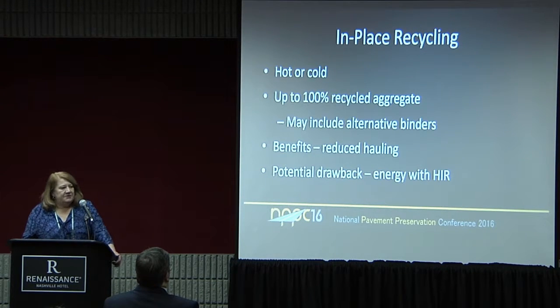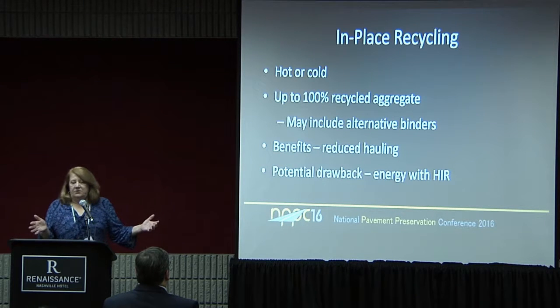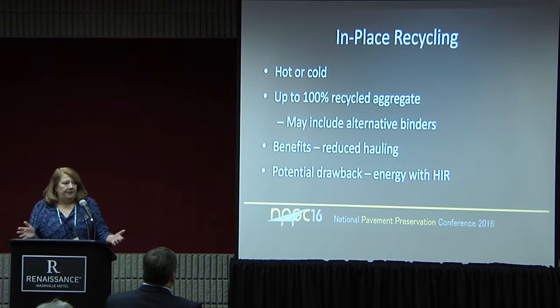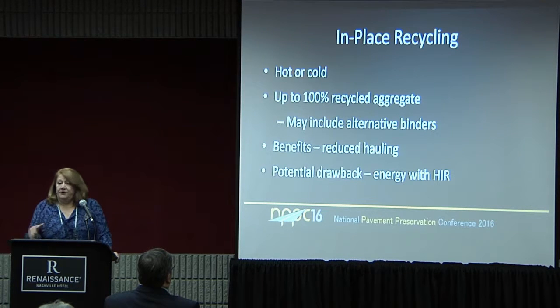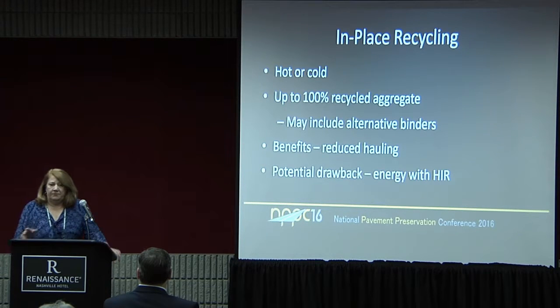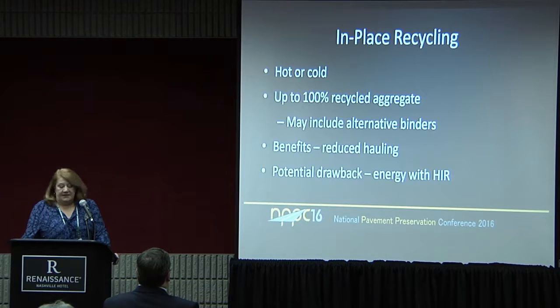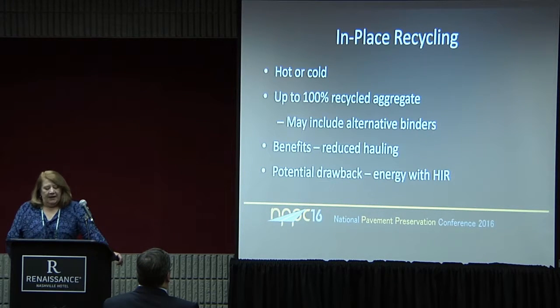Which leads us into in-place recycling. Almost by definition, it can be up to 100% recycled material. You can add additional aggregates if you need to, or as Kevin pointed out, if you need to extend or widen the pavement, which is a great application for in-place recycling, in my opinion. If you need additional material, you could put some RAP or virgin aggregate out in front of the recycling process and extend it that way. You get reduced hauling and all the good things that come with that, less fuel consumption.